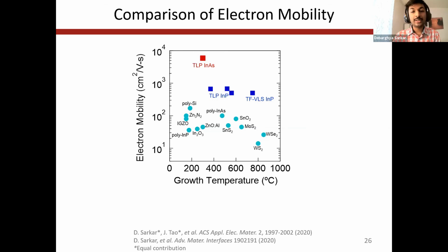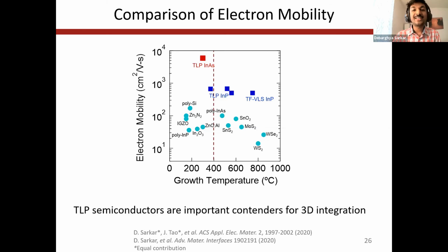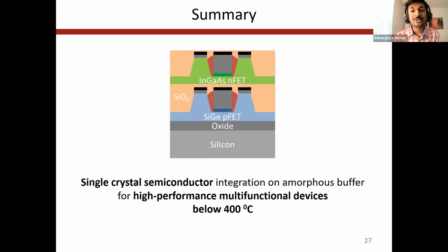Also importantly, this TLP indium arsenide was grown at a temperature of 300 degrees Celsius, and all of the device fabrication was done at or below 300 degrees Celsius, which is well within the thermal threshold of 400 degrees Celsius set by 3D integration requirements. So I can claim with some confidence that TLP semiconductors are therefore important contenders to be used for 3D integrated circuits in future. So in summary, my PhD research has tried to answer some questions and tried to explore and establish potential methods to achieve multifunctional high-performance devices and materials at a temperature below 400 degrees Celsius for 3D integrated circuits and flexible electronics applications.